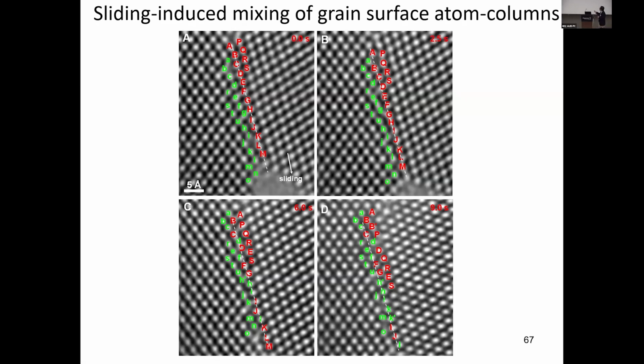So I mentioned the existence of these pentagon units at the grain boundary, and they are the intrinsic grain boundary dislocations. Actually, they can mediate the complex grain boundary deformation. For example, now we can track the motion of all the atomic columns here, right? Each white spot represents the projection of one atomic column. So we label all these surface atoms for the right grain by these red capital letters. We can also label all these surface atom columns for the left grain with green letters at the beginning. So at the end of this sliding deformation, you can see the mixing of red and green letters.